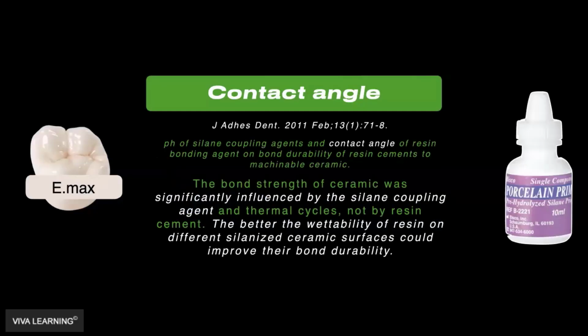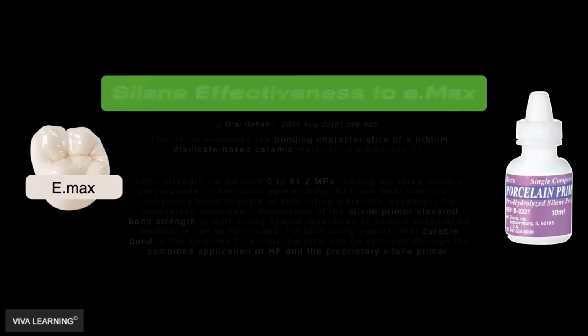And here's a study that was done in 2011, basically saying the different coupling agents change the contact angle. The bond strength of ceramic was significantly influenced by the silane coupling agent and not by the resin cement. The silane was more important than the resin cement. The better the wettability of resin on different silanized ceramic surfaces could improve their bond durability. Really important, right? That's what we're trying to do.